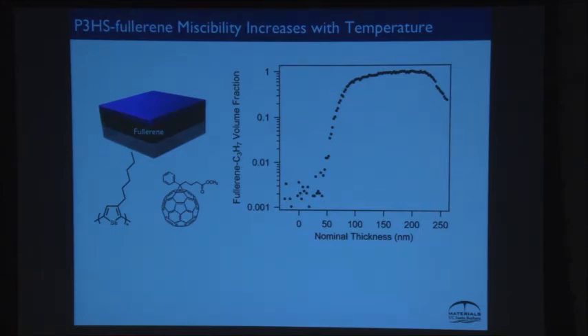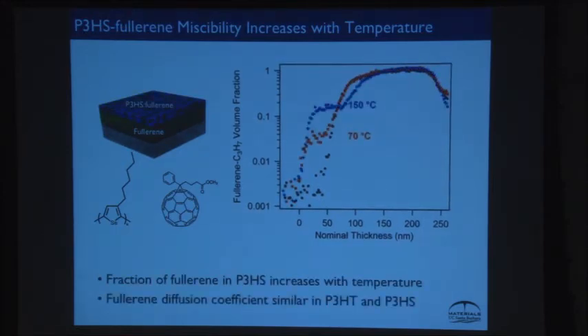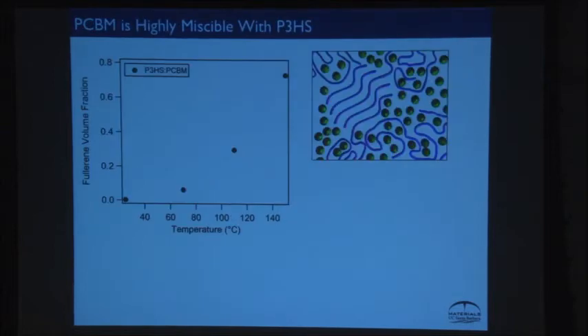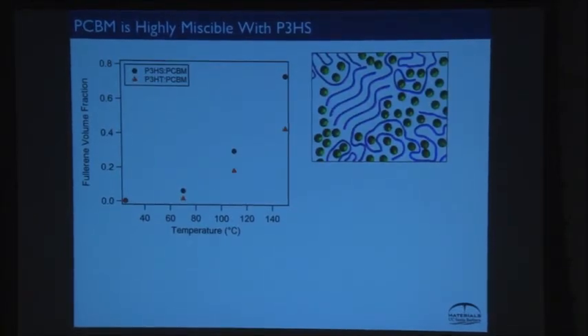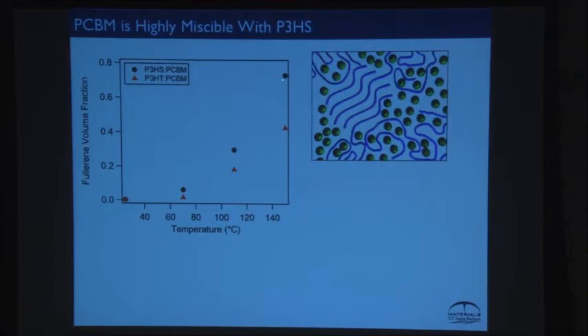So we actually measured the miscibility of the PCBM in this material, the same way we did before, had similar diffusion constant and so forth, and similar behavior qualitatively. But what we found out was that it actually was much more miscible in the P3HS. So somehow the interaction with the heteroatom or the crystallinity was such that in general samples of this tended to suck up more fullerene. And that meant we had more miscible fullerene around. And that's not good, we figure, for transport. And that was probably the origin of the poor fill factor.